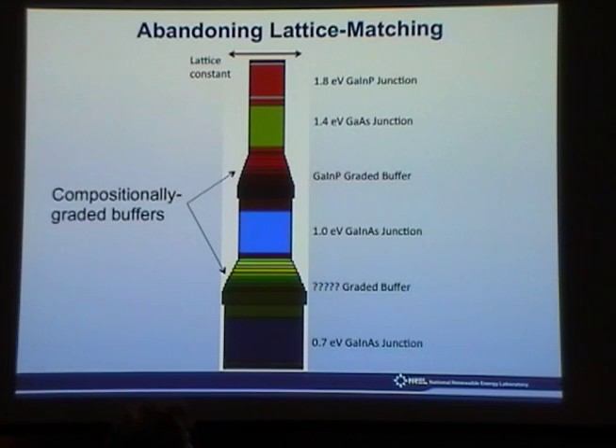And so a number of junctions are grown at one lattice constant. And then this junction is grown at a larger lattice constant, and this junction is grown at an even larger lattice constant. And these two graded buffers in between are a set of steps where we very slowly change the lattice constant in a controlled way, 10 steps, 20 steps, maybe we've changed the growth rate. We've done it with material that's transparent, so the light is being transmitted from here to here.